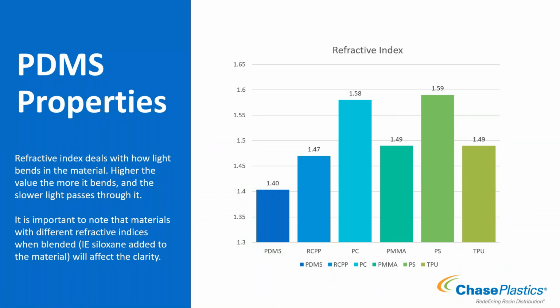And so looking at this gives us values for some standard materials. And you can see that your PDMS or your siloxane down there has a refractive index of 1.4. And you can see that it matches none of our clear products. And so if it is added in, you no longer have a clear product. So keep that in mind. And again, that's pretty similar for a lot of additives, where it's not going to necessarily match the refractive index of the base polymer. So you're going to affect the clarity. So do keep that in mind.